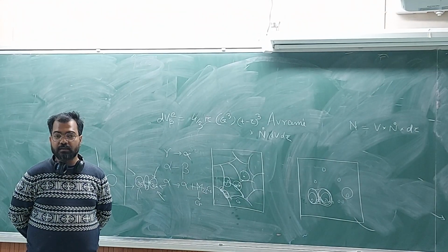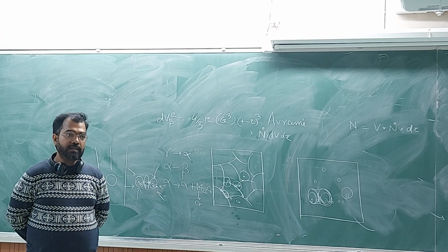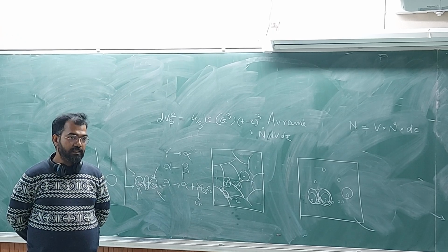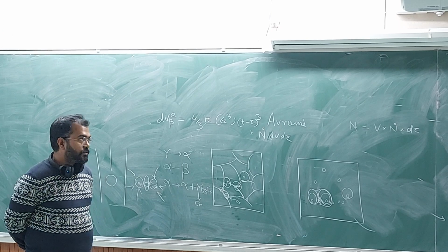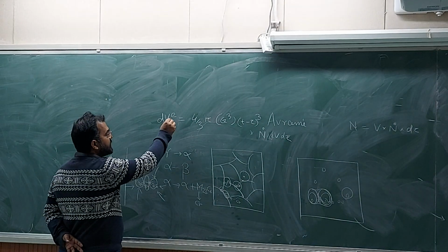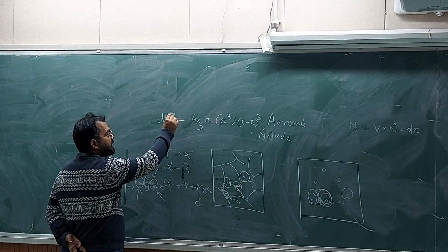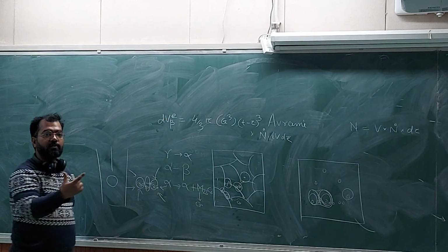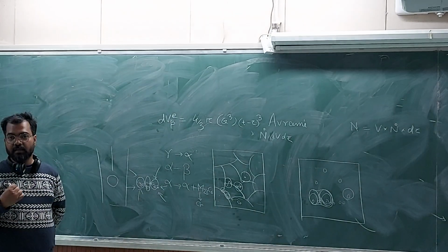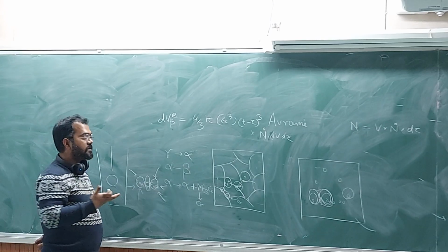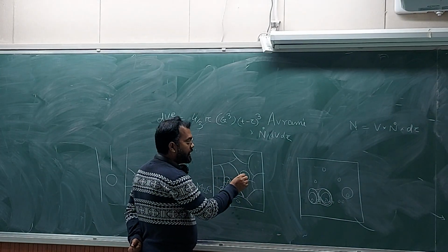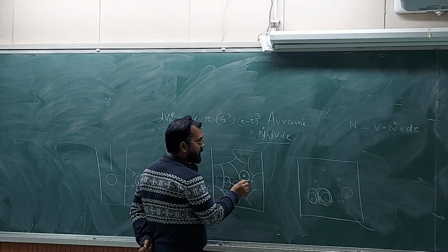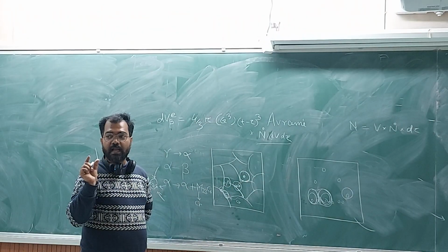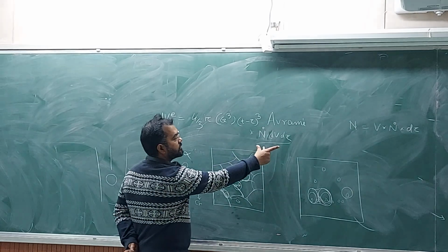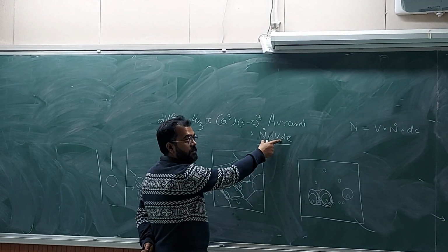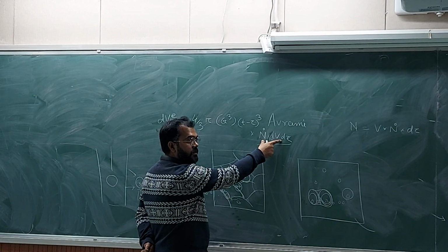So this was dV beta, which is the transformed region in Avrami. Okay, this you have read before. This is written with a superscript of E because this volume is more than what really transforms. It is called extended volume because you are not taking care of the new nucleation which is also happening in the transformed region. So we are not subtracting that volume. We must subtract this volume, right, where the nucleation has happened. That we are not doing.